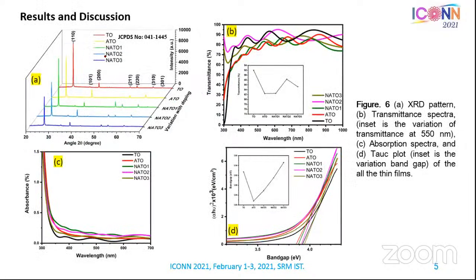So coming to results and discussions, all the as-deposited thin films show the JCPDS file number 41-1445, tin oxide, meaning tetragonal structure tin oxide. It is showing there are no secondary phases. The red color shows the pure tin oxide thin film, and with doping the intensity of the ATO decreased. Then again with doping of niobium it increased. The orientation of all the thin films is the 110 plane.